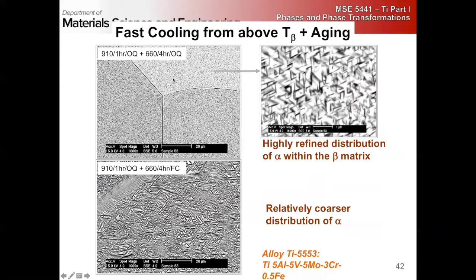So if we look at our oil quench and then aging for 4 hours at a higher temperature, we end up with a highly refined distribution of alpha. Remember, on the oil quench, we had an athermal omega formed. So what do you think is the likely nucleation site for this alpha? It's going to nucleate heterogeneously on the omega that formed, leading to a very fine alpha dispersion within the beta matrix. This is then oil quenched. If we do the same thing, but then furnace cool, our alpha matures quite a bit, and we develop a very classical basket weave type structure,